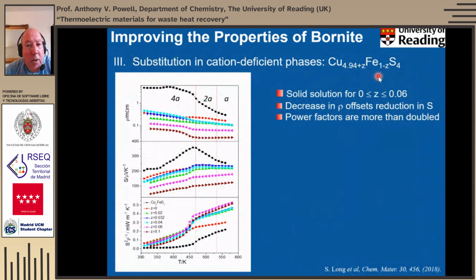So the final example I'll show is where we combined two strategies: we wanted to adjust the copper to iron ratio whilst also having some vacancies present. So this is no longer copper 5, this is copper 4.94. So we introduce some vacancies, we then adjust the copper to iron ratio. Once again, we see significant improvements in the electrical resistivity, which falls, which then feeds into quite large increases